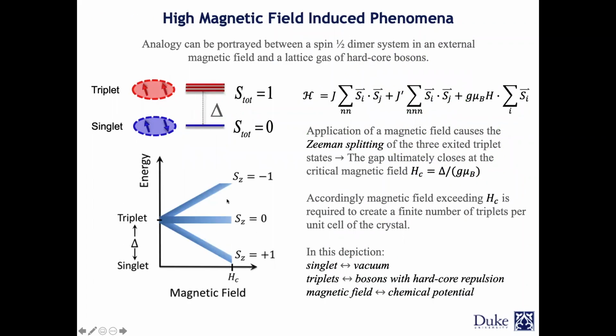Now, one other thing that's important is application of magnetic field. So if we start to apply magnetic field, we have a singlet triplet excitation or a singlet triplet gap, right? So we know that we are in a singlet state. If we start to apply magnetic field, we will have this Zeeman term that's going to kick in, and you have these 3 branches of the triplet as Sz = -1, +1, and 0, that can start to separate, and there's going to be a critical field at which these triplets start to condense into the ground state. So in this scenario, it is actually very much like Bose-Einstein condensate physics. So your singlet is the vacuum, your triplets are bosons with hard core repulsion, and your magnetic field is a chemical potential. So let's see what can be done with this.